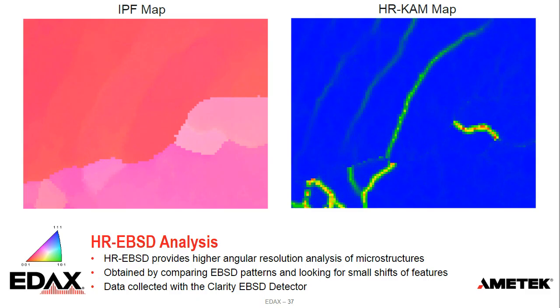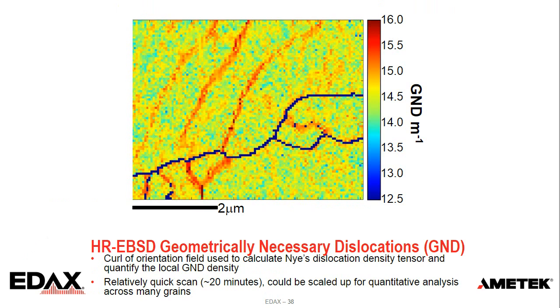This can then be used to measure the GND, or geometrically necessary dislocation density. This is a measurement that's basically, depending on what the misorientation is, there's a certain amount of dislocations that are necessary to create that angular change. It's the curl of the orientation field that's used to do that calculation. So we can figure out where the GNDs are present to visualize those.